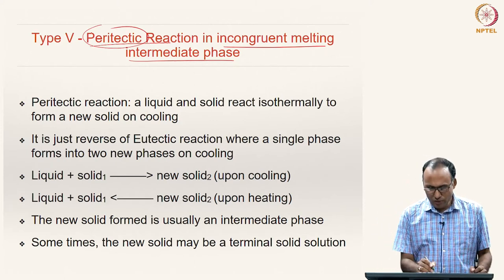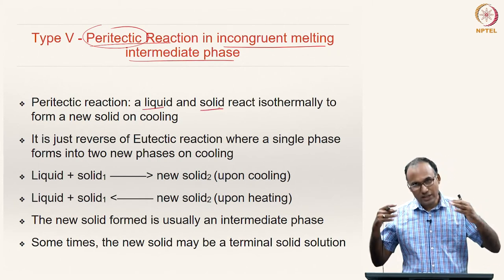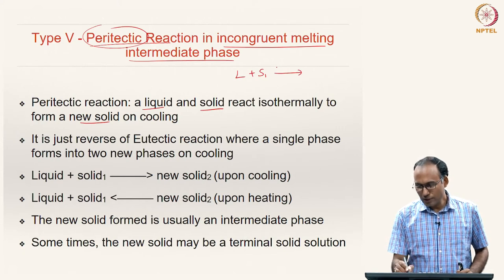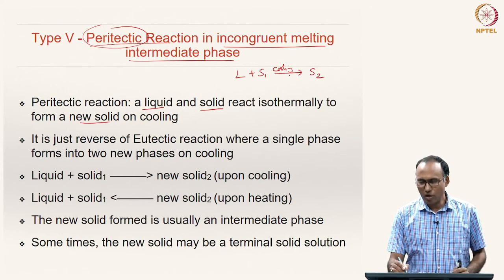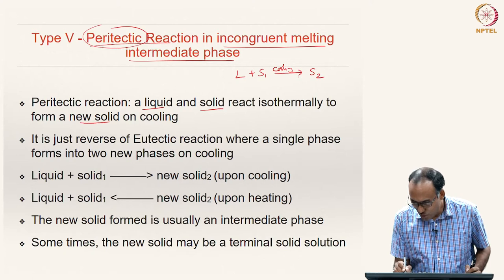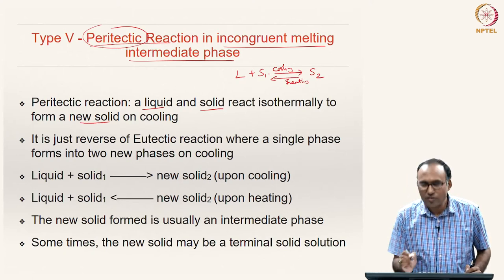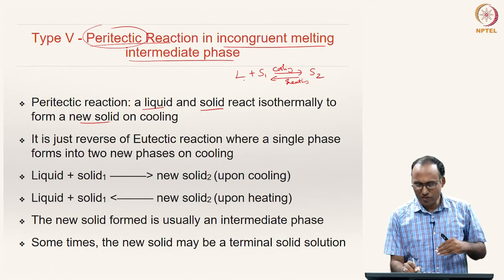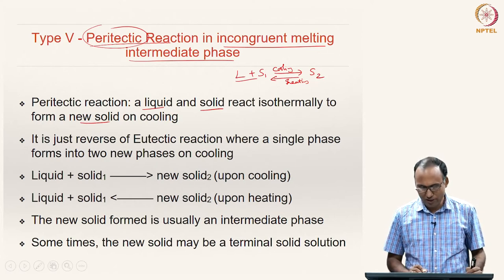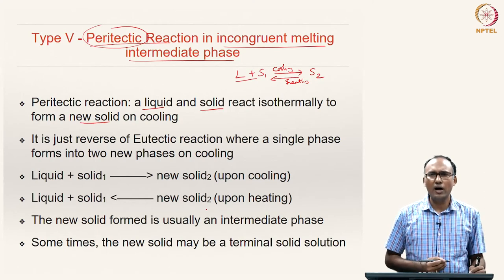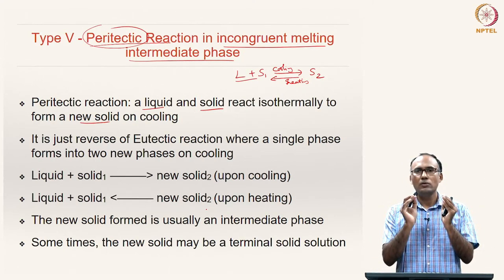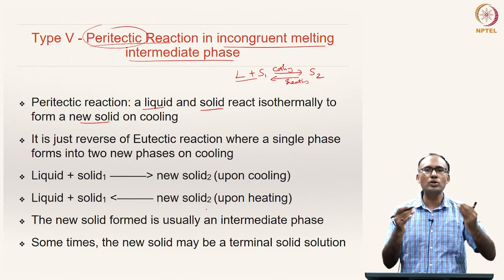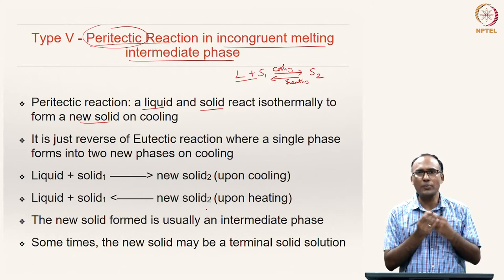What is a peritectic reaction? A peritectic reaction is one in which a liquid and a solid react together isothermally to give a new solid. Upon cooling: liquid plus solid₁ gives you a new solid₂—that is the peritectic reaction. You can also say that upon heating, a solid gives a liquid plus solid₁, which is also the peritectic reaction in reverse, but we are focusing on solidification. This means two phases give you one single phase, whereas in a eutectic reaction one phase gives you two phases—it is exactly opposite to the eutectic reaction in terms of number of phases before and after.